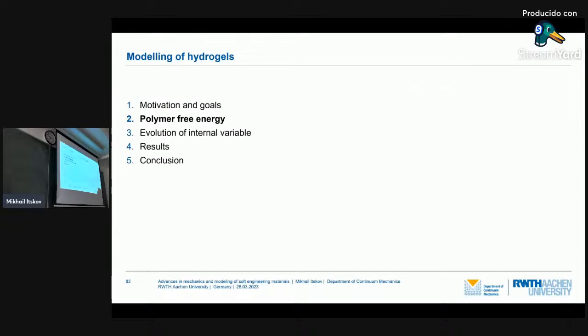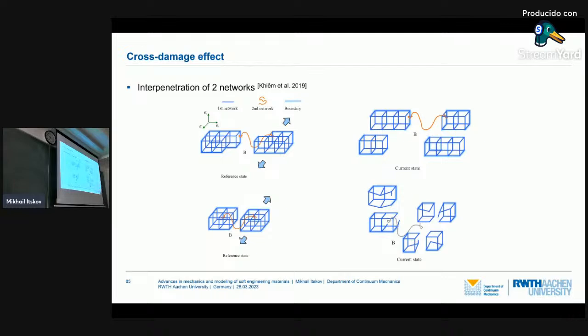A very short message on how we deal with the modeling of it. Skipping some slides, the problem was the so-called cross damage effect in these hydrogels. We studied, for example, double network hydrogels, which have two networks, and the problem was that if you apply some tension, the damage appears not only in the direction you apply it. This is shown here. You apply the stretching, and this damage also appears in the cross direction. That is why it is called the cross damage effect.